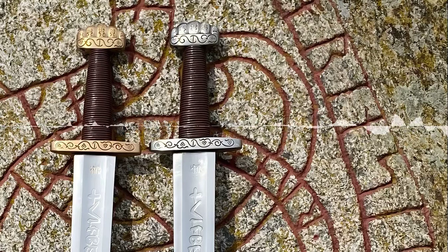And with the Ulfberht? The sharper blade cut itself free from the wood instead of getting stuck. And this high-quality steel was uniform and free of impurities, so it could be heat-treated optimally. Hard enough for a sharp edge, but with proper tempering also tough enough not to break. That made the blade more reliable in combat. So you stay in the fight. You keep the initiative. That's vital for survival in close combat.